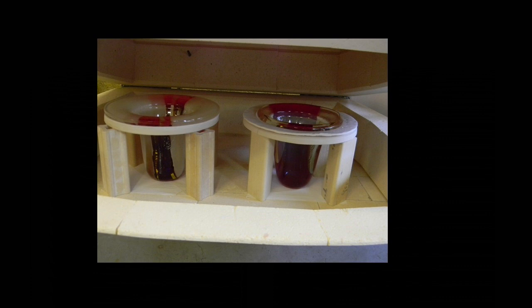These are 5-inch kiln posts. You would select the dimension of the kiln post based on the depth of your kiln. The deeper your kiln, the taller a drop vase you can make. Also notice that 1/8 inch thick fiber paper on the right-hand piece of art is really obvious in this image. You don't want to skip that step, or your glass frequently will drop right through that hole and you'll have a puddle on the bottom of the kiln.